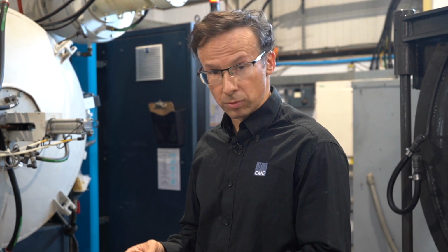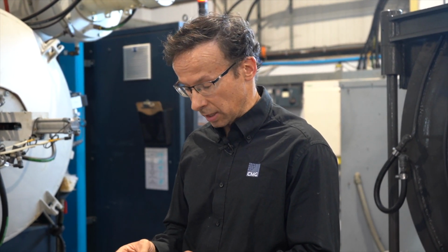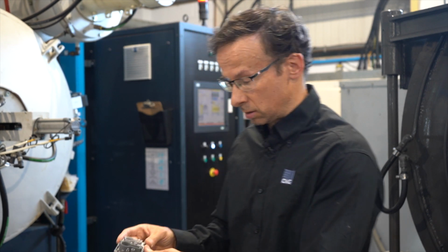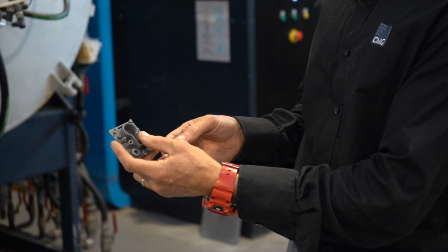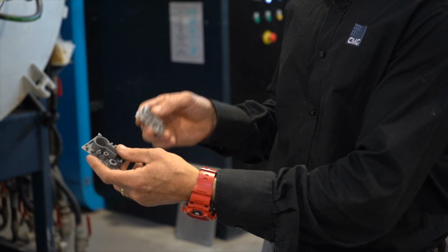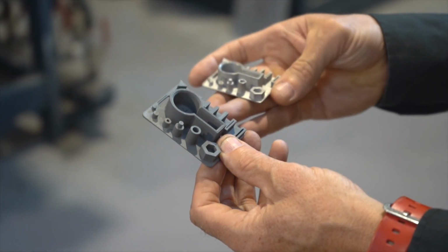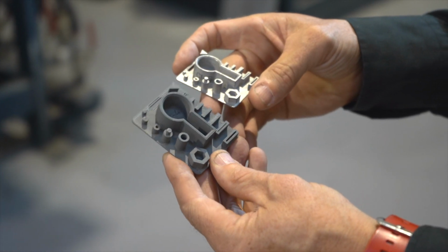So one thing we've got to mention is the shrinkage. This component was designed with a 20% in the X and Y and 26% in the Z. So if you can see as I'm holding up, there's quite a lot of difference. So that shows what's happening at the shrinkage side of things once it's been sintered.